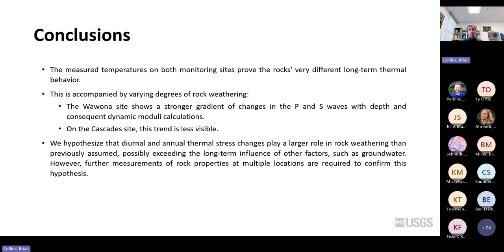And we hypothesize that these are caused by the diurnal and annual thermal stress changes that affect the rock, and that the influence of the temperatures is actually higher than the influence of other factors such as groundwater, because we didn't see any cracks or joints where the groundwater can flow. Obviously, we need some more measurements from multiple locations to confirm this hypothesis. But I think the results are quite interesting.